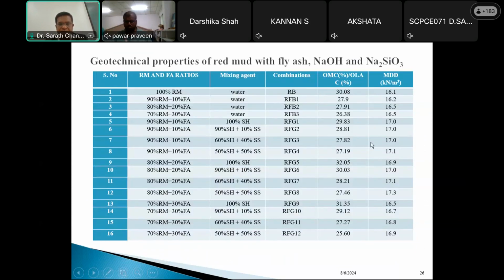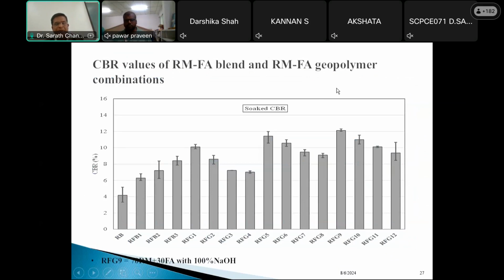That's why I projected this also, because it's not just water. We need to mix these solutions in a proper way, and that solution has to be presented as an OMC for these combinations. And the CBR values of red mud fly ash blend and red mud fly ash geopolymer combinations. So here, red mud fly ash and red mud fly ash with geopolymer. RFG9, which has 70% red mud plus 30% fly ash with 100% NaOH, has shown the highest CBR, approximately 12.1%.